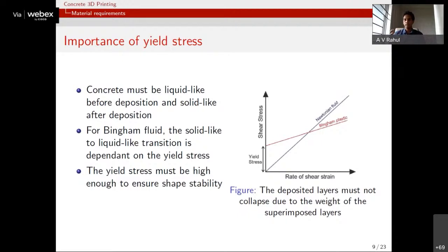This high yield stress ensures that once the material is pushed out from the nozzle and there's less stress on the material, flow is prevented and it is able to retain its shape. But during pumping, we use a specially designed pump to go above its yield stress and initiate flow in the fluid. So we use a specially designed pump to pump this high yield stress concrete. But once it's deposited out from the nozzle, the high yield stress ensures that the concrete can retain its shape.